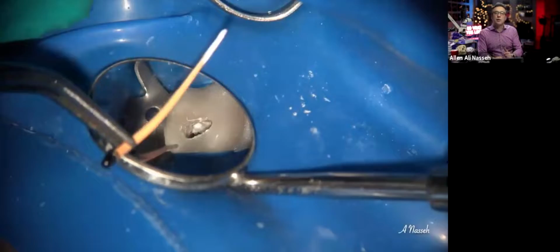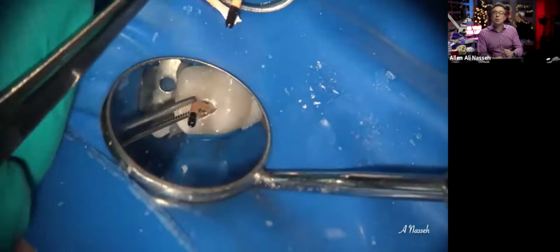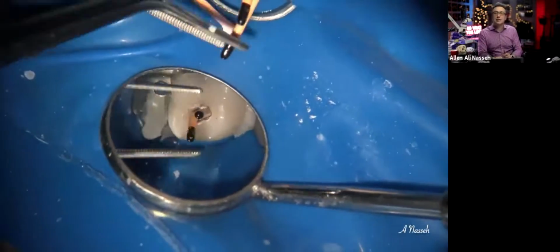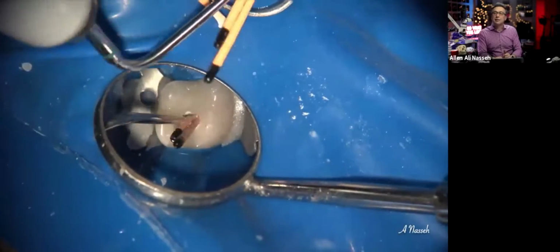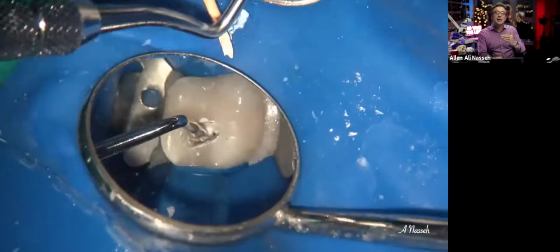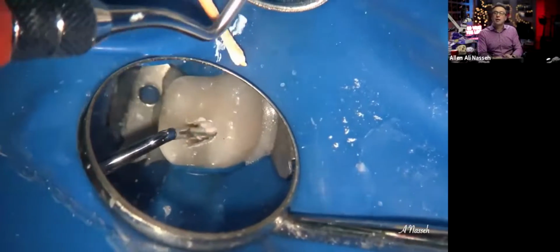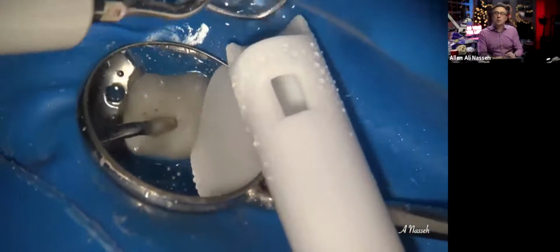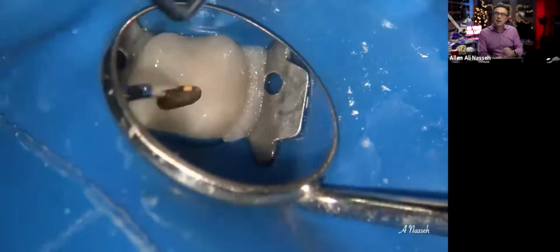So we put the 40-04 in, and you can see I only melt the gutta percha about 1 millimeter or so above the orifice and come back immediately while it's still molten with the largest plugger, a Schilder plugger, like a size 10 plugger, and plug it down, almost creating a nail head that allows me to then cover the entire orifice with gutta percha. So after I remove the sealer with the ultrasonic and water, where it comes out very quickly and cleanly, I'm only showing gutta percha at the orifice level, as you can see.